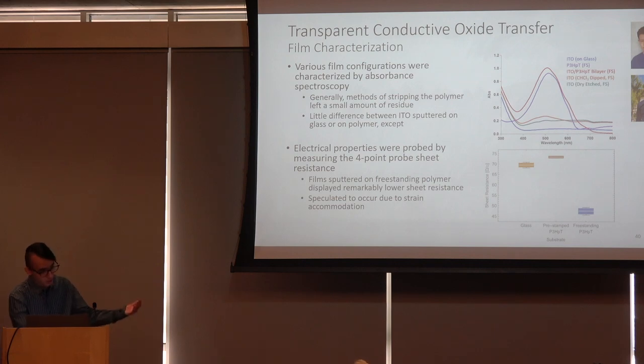And we need to do additional structural characterization to verify if this hypothesis is true. But what we think is happening is essentially that sputtering is known to lead to residual embedded stresses at interfaces. There's a variety of reasons for why this happens, but part of it is due to the fact that there's local heating happening at the interface as you're depositing. And then your two materials will typically have different coefficients of thermal expansion. And so as your material cools, there's strain that is suddenly induced at that interface due to that thermal expansion mismatch. And that strain can potentially lead to all sorts of defects, such as dislocations, which are exceptionally effective at trapping charge in semiconductors.